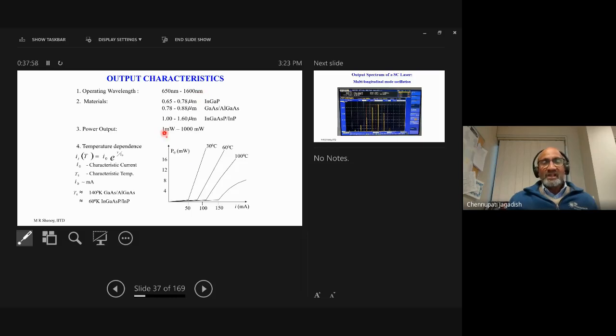And this is a case showing the output power of a laser diode with respect to the injected current. You can see that below the threshold you end up getting very low amounts of light, essentially spontaneous emission, and they act like light emitting diodes. Above the threshold, they act like coherent light sources, like laser diodes. You can see a very linear power increase taking place above threshold, so very efficient light emission. But this is also very much dependent on the temperature of the device as well.